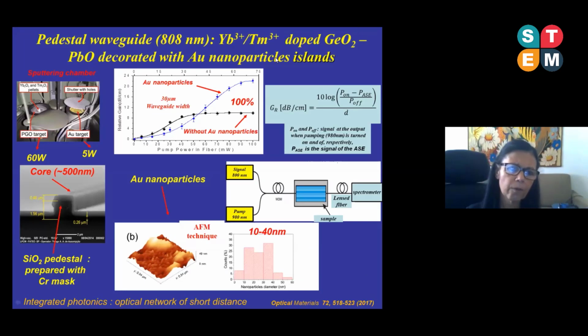Well, starting with the one prepared to operate at 808 nanometers. In this case, the core was prepared using ytterbium and thulium ions, the same composition, of course, and it's a waveguide decorated with gold nanoparticle island. In this figure, I show you the experimental setup used. It's again the inside of this sputtering chamber. We have the two electrodes. Over one of them, we place the target of the matrix with pellets. Pellets are the small targets we produce, made of ytterbium oxide, thulium oxide. Over the other electrode, we have, as I said before, the commercial target of gold with that shutter with holes placed above it.